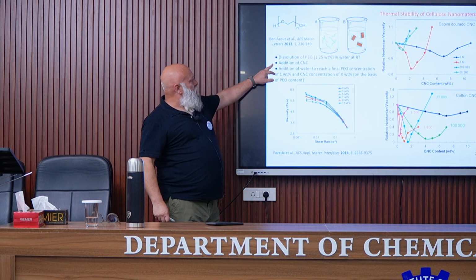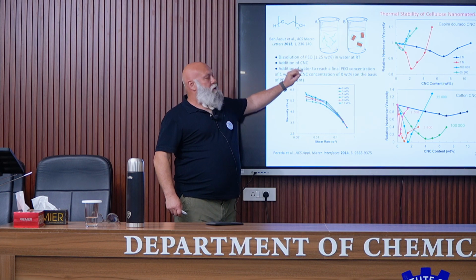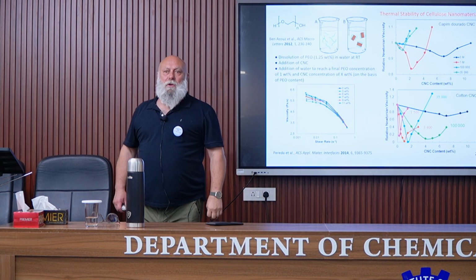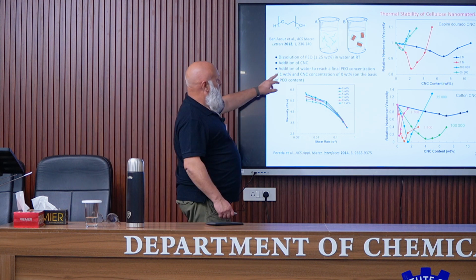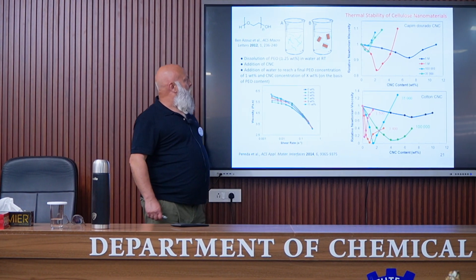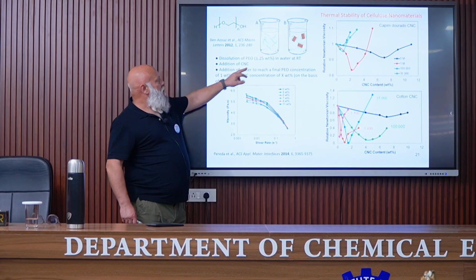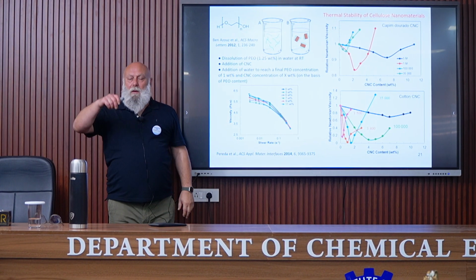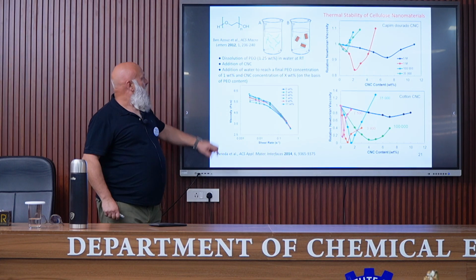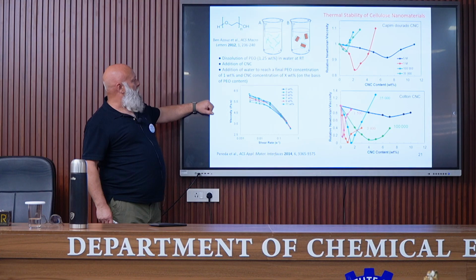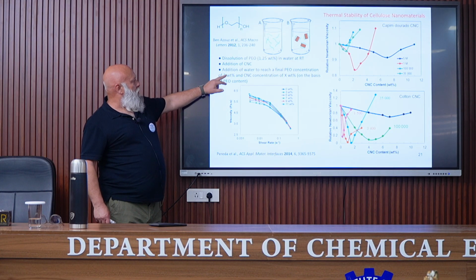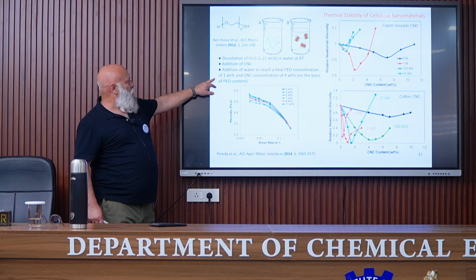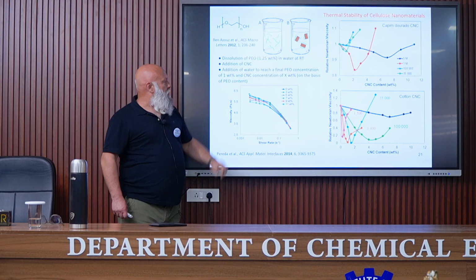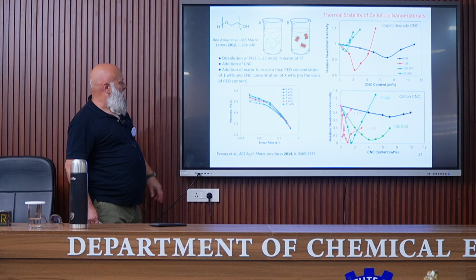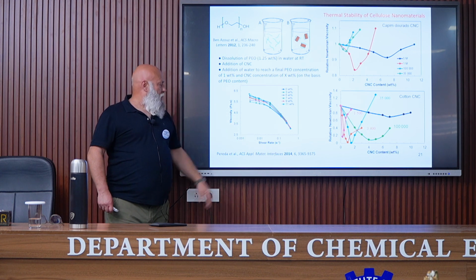So the thing is that we used polyethylene oxide. Polyethylene oxide is a water-soluble polymer. It was dissolved in water at room temperature, 1.25%, and then cellulose nanocrystals were added in different contents in this polymer solution. Addition of water was performed to reach a final concentration of 1%, and you can determine the concentration of cellulose nanocrystals. The viscosity of the dispersion was determined.